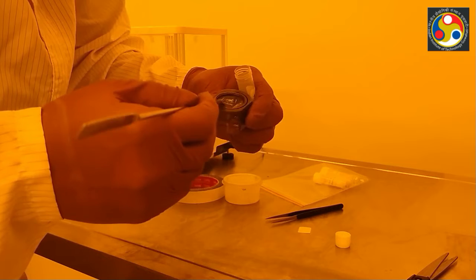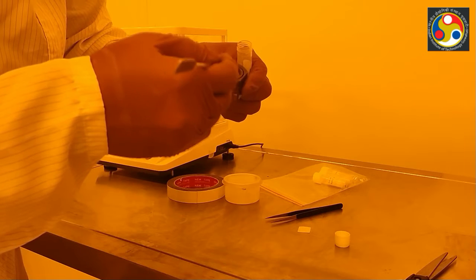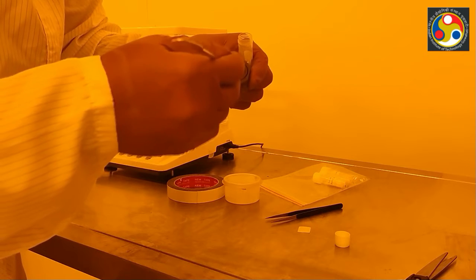We have to use a very small amount of sample, and we have to spread the sample in a thin layer above this carbon tape. This carbon tape is a conductive tape, and we need it because the machine will give some electrons into this sample holder. For those electrons to discharge into earth, we need this conductive tape, and above the conductive tape we are spreading our sample like this. So my sample is now spread evenly all over this conductive tape.